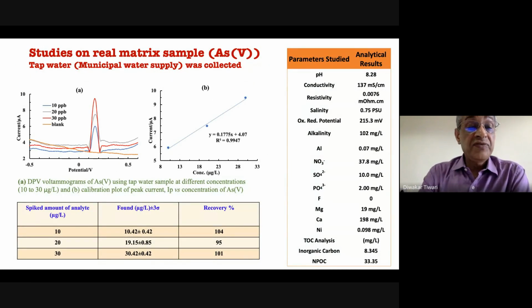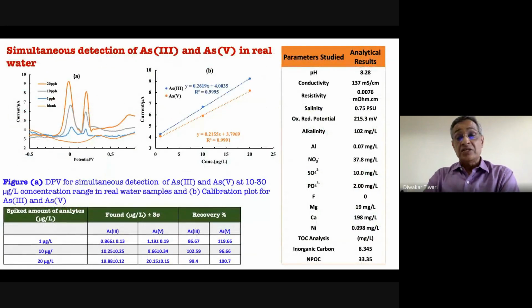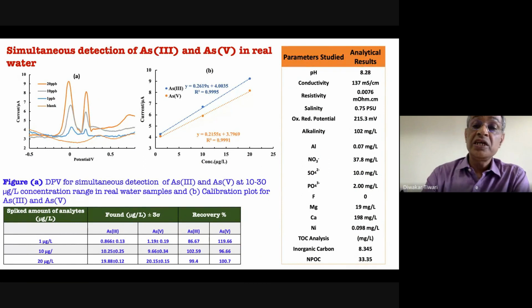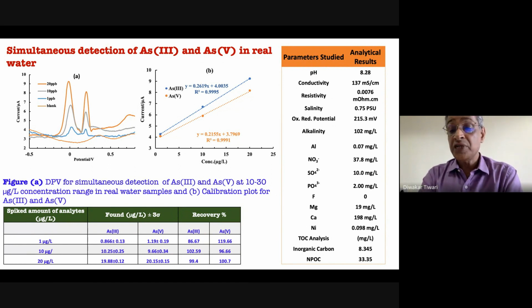So similarly for the arsenic 5, we have conducted for the real water, and here again a good recovery that we have obtained, and a good calibration line with the R square of 0.9947 that we could get. So there was a real challenge for detecting these two, arsenic 3 and arsenic 5. And I will say that this is one of the things that we have conducted; I have not seen direct detection of these two oxidation states of the arsenic, and that we have done, in the simultaneous detection in the real water also, and both are detected very nicely. And we can see that a good calibration line is being obtained, and the two different peaks for the arsenic 3 and arsenic 5 have been observed, and recovery percentage was also very high.